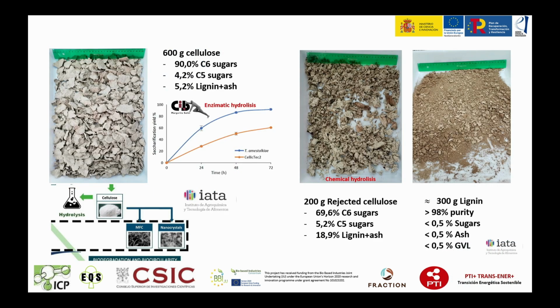We separate the high purity cellulose from the less pure cellulose by a screening method. And as I said before, the high purity cellulose we give to the IATA or to the Center of Biological Research Margarita Salas, where they use it to perform an enzymatic hydrolysis. We also obtain a high purity lignin that has no odor and has lower contents of sugars, ashes, and solvent. And this lignin we also give to the IATA, where they use it as an additive for packaging. And the cellulose with less purity, we use it to perform a chemical hydrolysis to convert it also into